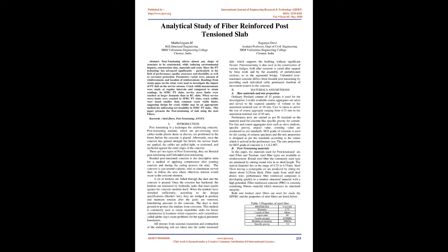In SFRC PT slabs, service stress limits were reached at larger demands than in RC slabs. When service stress limits were reached in SFRC PT slabs, crack widths were much smaller than common crack width limits, suggesting design for crack widths may be an appropriate method for addressing serviceability in SFRC PT slabs. This paper presents the post-tensioning of slab using the steel fibers.